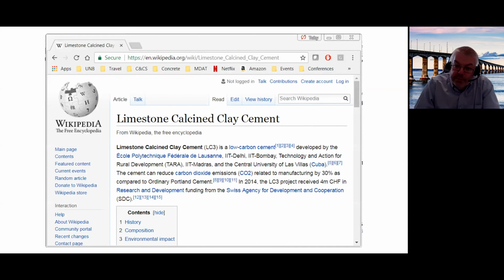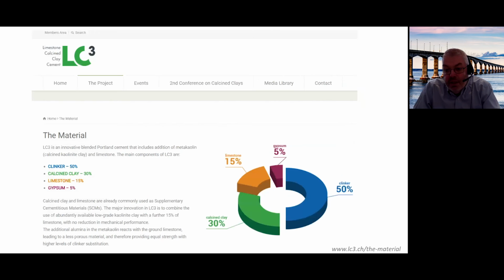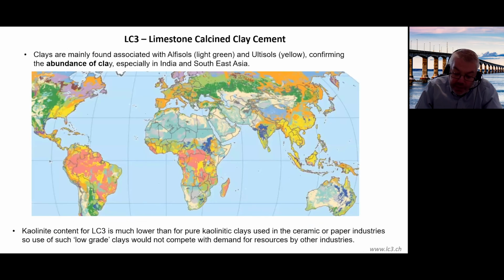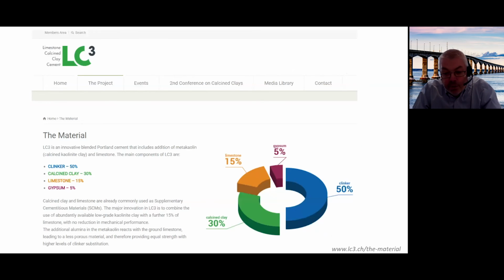I'm not going to talk much about limestone calcined clay cement. It's just an example of some innovation. This is a material that only contains 50% clinker. The remainder is made up of calcined clay, limestone, and of course the gypsum that you would normally have in a Portland cement anyway. This relies a lot on the normal pozzolanic reaction between the calcined clay and the calcium hydroxide that's released by the clinker, but also on the reaction between limestone and the alumina in calcined clay. It actually allows us to use limestone as a cementing material, because it's reacting with the alumina in the clay.